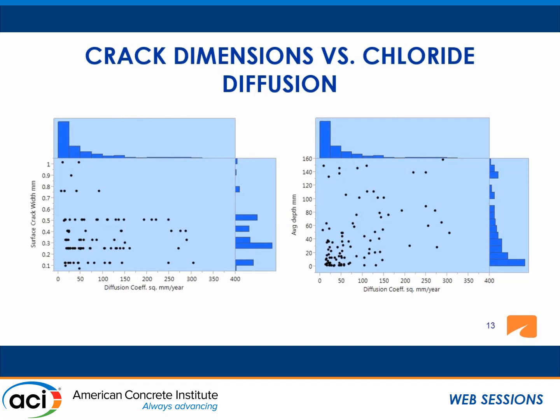The plot on the left shows the correlation between crack width and the diffusion rates. As you can see, it might be hard to visualize this, but the distribution on the y-axis for the crack width shows that it's not really a clear relationship going on there. Even for crack widths above 0.1 mm, we see significant diffusion coefficients.